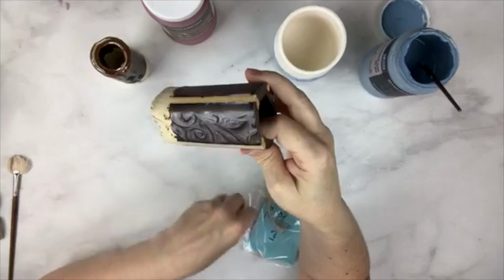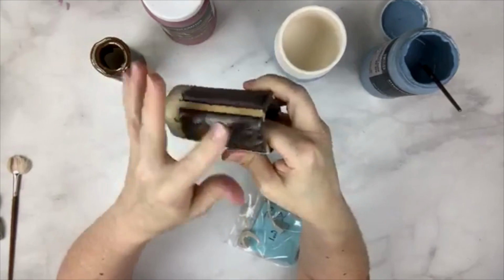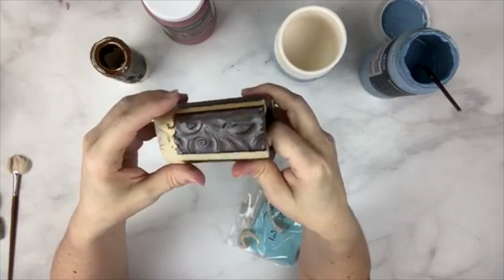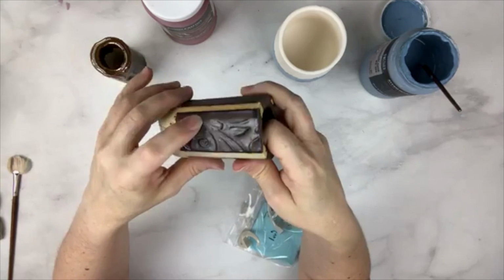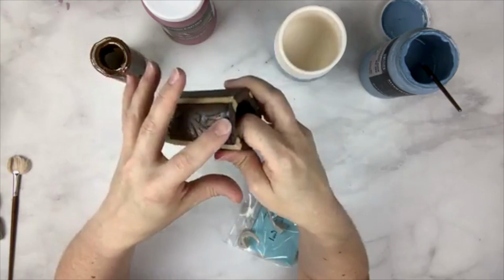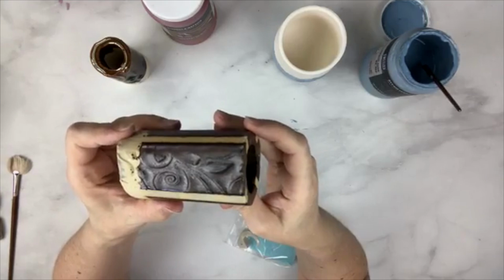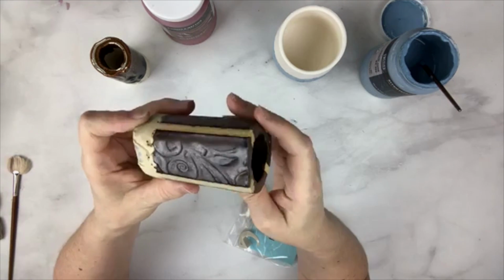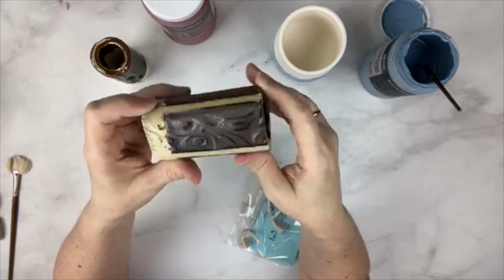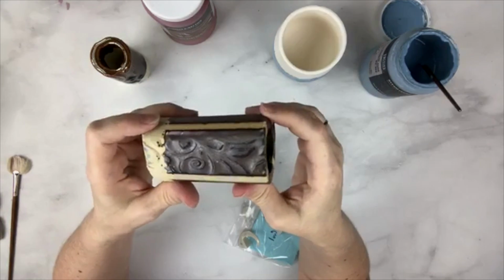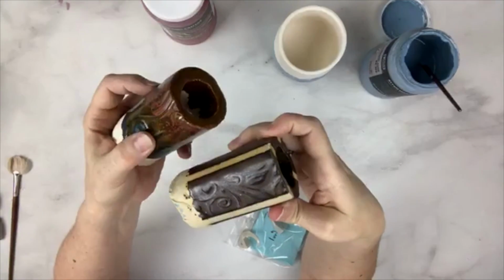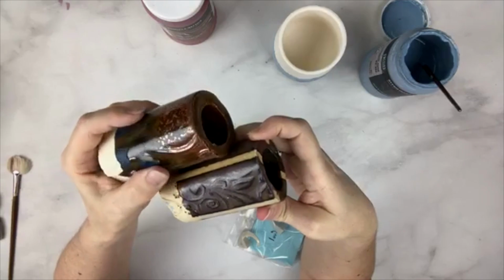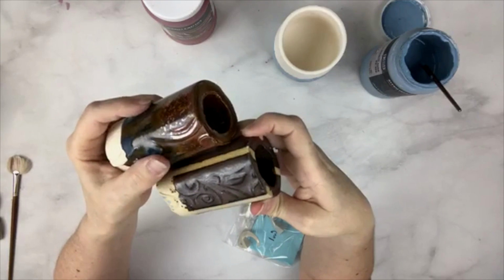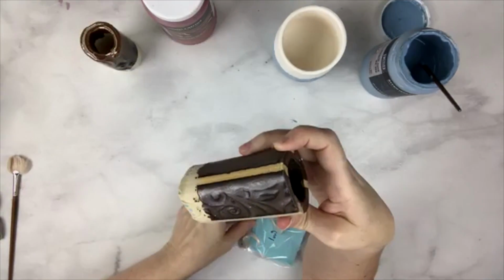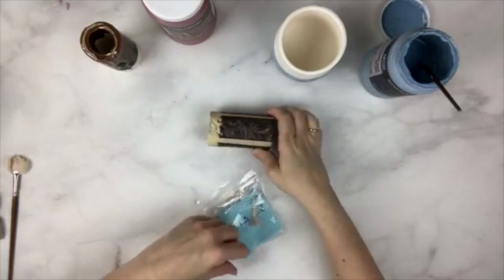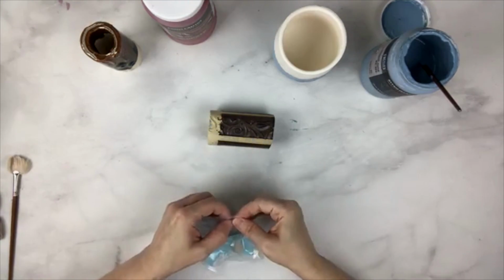So what was happening is that the firing was reaching the right temperature, the right amount of heat work, but the slow cool was encouraging the growth of microcrystals, which was making it look almost exactly the same as the cone 4 firing, kind of dull, brown, not really what people were looking for. Certainly not this kind of result. Let's see if we can see those crystals. It looks like a totally different glaze, doesn't it? And the only difference was the slow cool schedule and 1 cone difference.